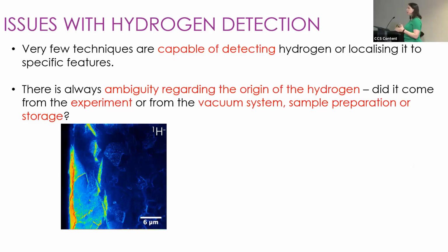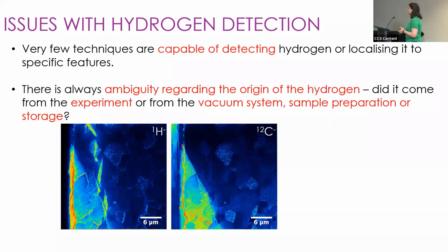So because we have the ability to map multiple elements in the NanoSIMS, if we look at the carbon map, things start to become a little bit clearer. We can see it follows the same distribution. Because we have resin over here, what has happened is that we have taken about half an hour to image this whole area. And in that time frame, when we're not imaging over here, hydrocarbons from the resin have diffused over the sample surface, bringing in hydrogen with it and complicating our analysis of hydrogen. So that is why we typically don't want to look for hydrogen in the NanoSIMS.